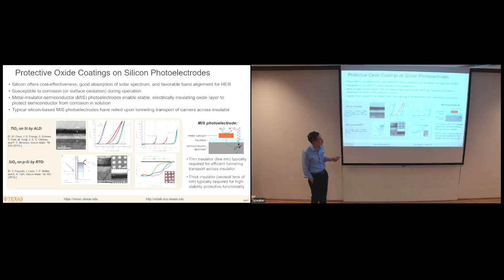Now, one approach to doing this, which is mostly what has been done in the literature, is to say, well, we'll just make this protective layer extremely thin, maybe on the order of 1 to 3 nanometers. And then when it's that thin, the carriers can tunnel across them, all right? But if you really want this to be a good protective layer, 1 to 3 nanometers may not be sufficient. You really want most likely something that is several tens of nanometers in thickness. And then the tunneling probability will be essentially 0, okay?